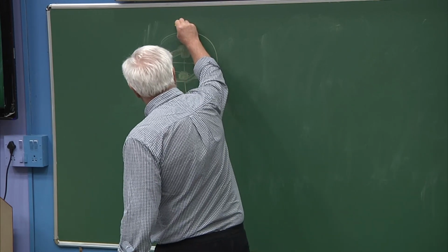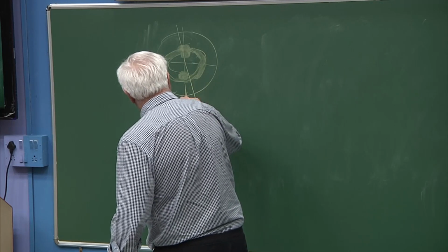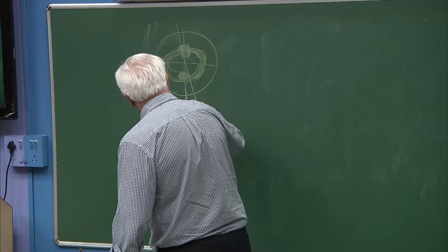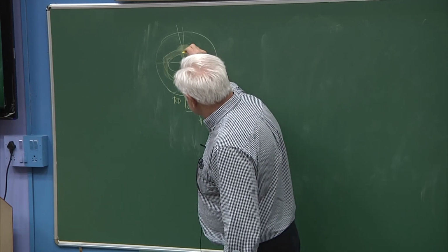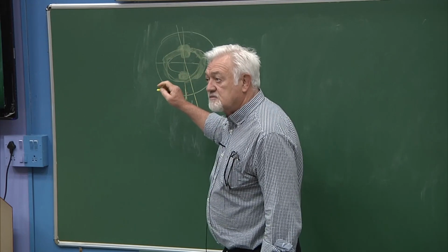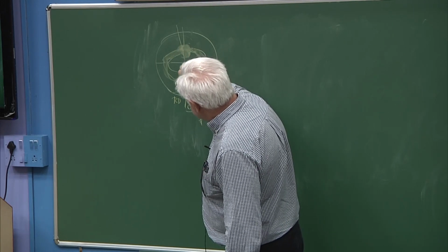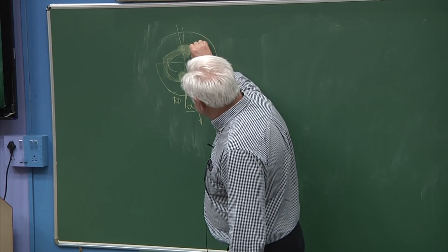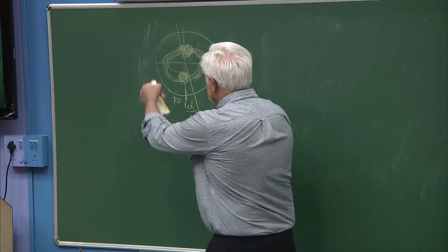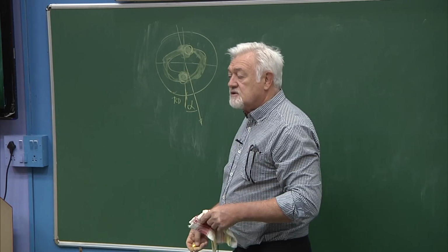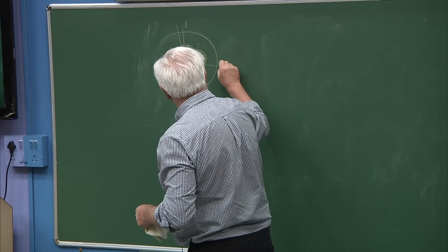But if you now do a tensile test at an angle alpha, so this is the rolling direction, and you do a tensile test at an angle alpha on this texture, the symmetry of the sample is not orthotropic anymore, because it has, as you can see, this strong component here and this strong component here on the sides. So the tendency if you do this is that you probably are going to develop some shear. So this is the component one, this is the component two.